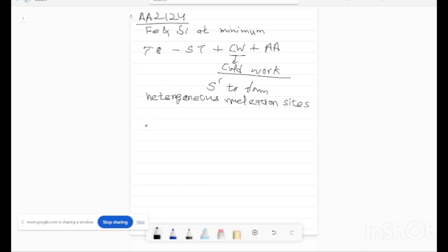The 0.2% proof stress of T8 condition is 415 MPa, and it is mostly used in aircraft parts, manufacturing of aircraft parts.